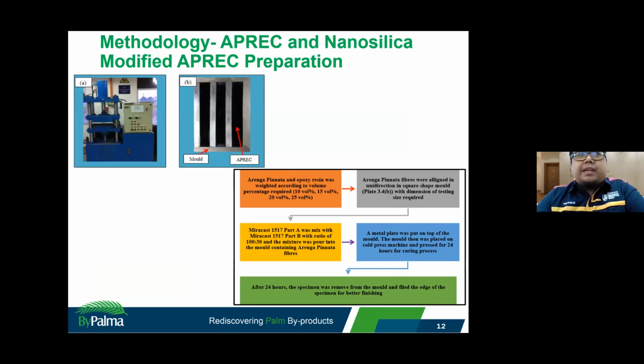Aida. Okay, and then we move on to the preparation of the APREC, or Arenga Pinnata reinforced epoxy composite. So for the preparation of nanosilica modified APREC, the steps are the same as the preparation of unidirectional APREC. Okay, the steps are the same. First, Arenga Pinnata in epoxy resin was weighed according to the volume percentage required. Then the Arenga Pinnata fiber was aligned in the mold, a rectangular shape mold, in one direction. The mold size is 250 millimeters in length, 25 millimeters in width, and 3 millimeters in thickness.